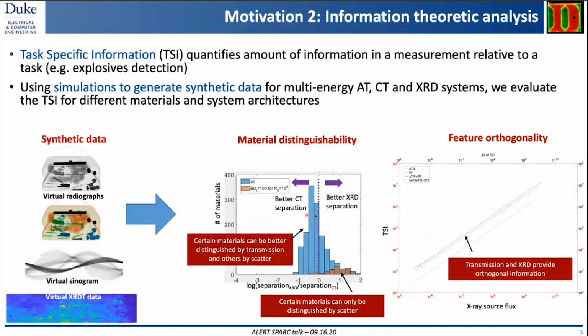And so this histogram in the middle, it was an experiment that we had done looking at the inherent distinguishability of different materials in the transmission or the diffraction space. And so it's a histogram showing how many materials have some degree of separation between them. And I won't go through the technical details, but basically it boils down to the fact that on the left-hand side of this dashed purple line, all the materials that show up in this bar chart are better separated via CT. So their density or Z effective are perfectly sufficient that they are more separable through a good transmission measurement than a diffraction measurement. On the right, it's materials that are better separated from one another via X-ray diffraction.